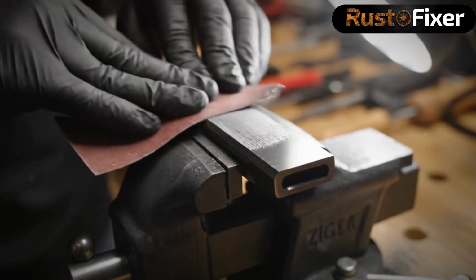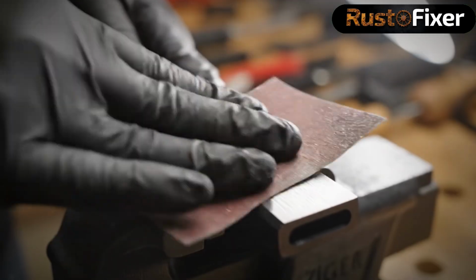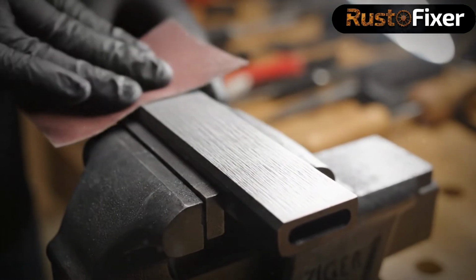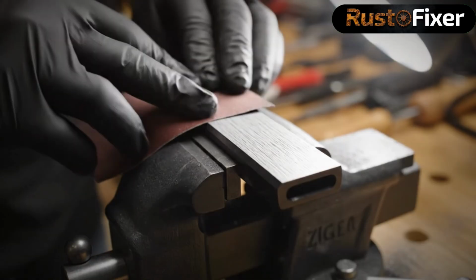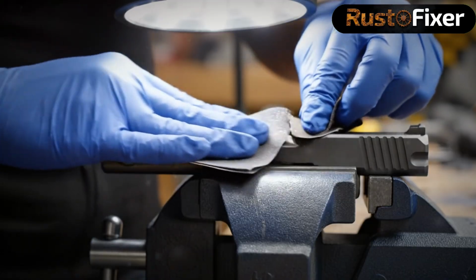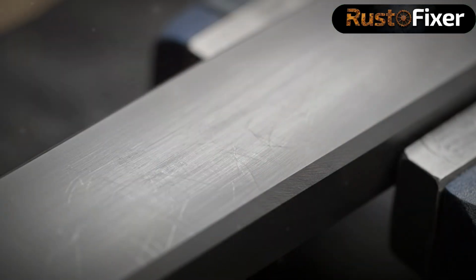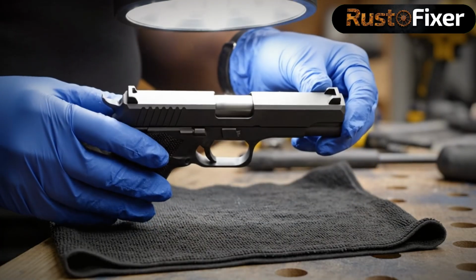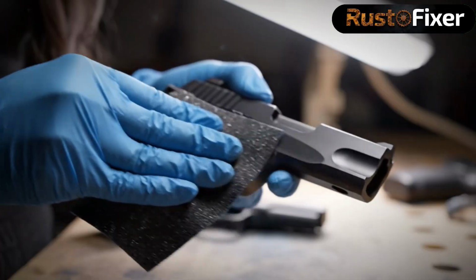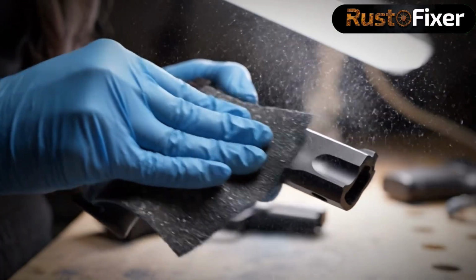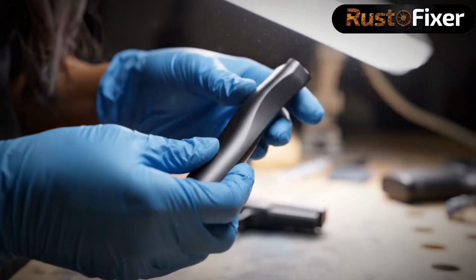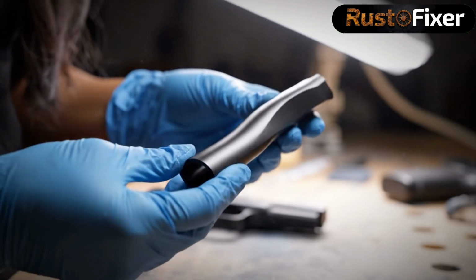The slide's flat surfaces receive special attention. Fine sanding in consistent directions creates a uniform grain that will ensure the Cerakote adheres well. The progression continues. 400 grit, then 600 grit, then 1000 grit sandpaper. Curved and contoured areas of the slide are fine sanded with flexible abrasive pads or fine paper wrapped around shaped tools.